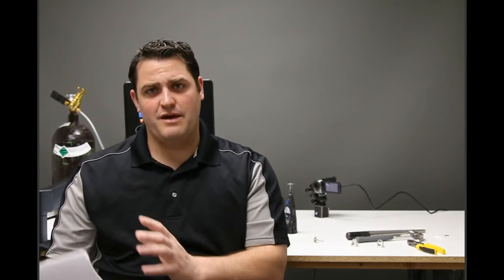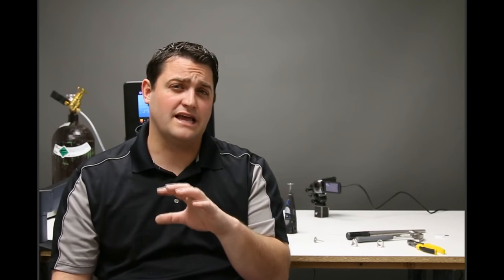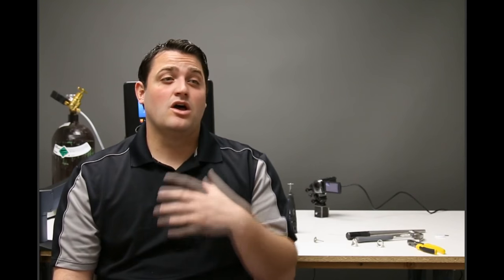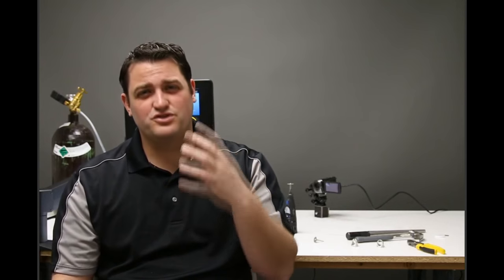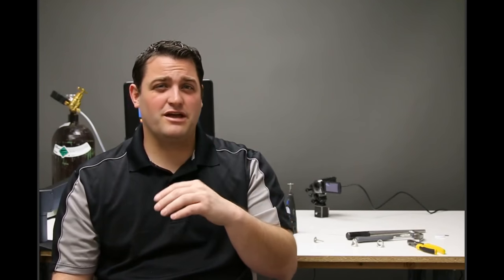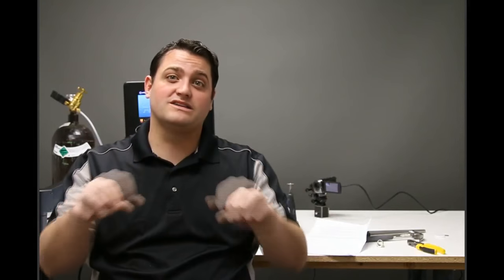One of the biggest questions that I get, and I'm going to shift gears back to the Orion, and this goes to both Orion and laser, is: my silver welds are super brittle. As I bring them together and weld, as soon as I put even just a little bit of heat into it, I get cracking. And that's normal. Basically, it's because silver has the ability to wick the heat away really quickly, right? The conductive heat is pulling the heat from the weld site and spreading it throughout that piece.